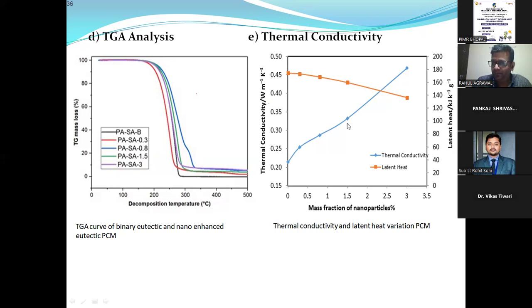This is the curve that we will focus on more: as we are increasing the concentration of the nanoparticles, the latent heat decreases. As the concentration of the nanoparticle increases, the latent heat value decreases. So what should be the optimal point? How much can we incorporate, because when we are testing, we need the maximum amount of thermal conductivity and we need the maximum amount of latent heat also. So the crossing point between the thermal conductivity line and the latent heat is the optimal point. Means approximately up to 2 to 2.5% of the nanoparticles we can incorporate.